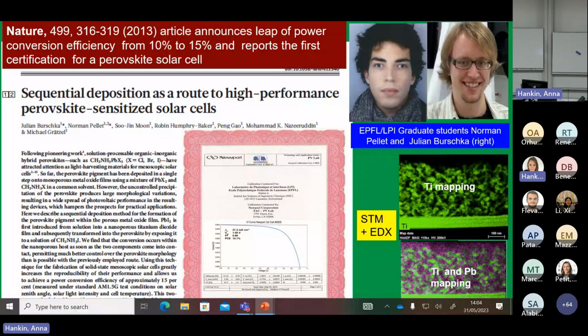And we developed sequential deposition, which means solution processing. A lot of people just put all the components in a solvent and they print the paste or the solution and heat it, and that gives you perovskite. However, we found it was very interesting to just use the lead iodide first and convert it. And so that is actually now for us giving the highest efficiency. I'll show you that efficiency figure later. And so we're going back to a 2-step sequential method to get the top efficiency cell close to 26%.